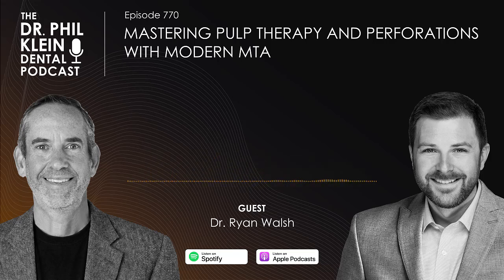Yeah, absolutely. So as it's placed initially, you're going to place it in contact with the pulp tissue. And so initially what's going to happen is there's going to be a big spike in the pH. In other words, you're going to go from a body neutral pH up to about 12 and a half, give or take. And that's going to initially cause a superficial layer of necrosis, about a millimeter or less thick in the pulp tissue.